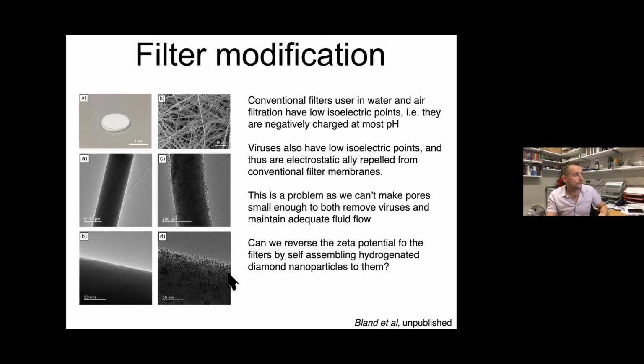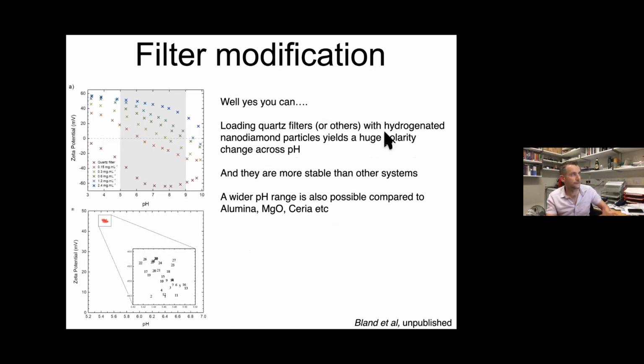So what happens when you do this? Are we able to get enough on there to switch the zeta potential? And obviously, yes, because otherwise why would I be presenting it? So this is the zeta potential of a quartz filter here, right? This is measured by our streaming potential apparatus. You can put a bulk sample and measure it. And then Henry just keeps putting diamond particles on it until he can flip the potential over, right?